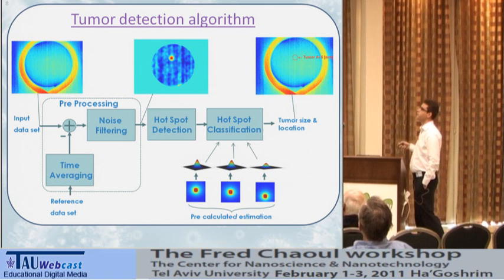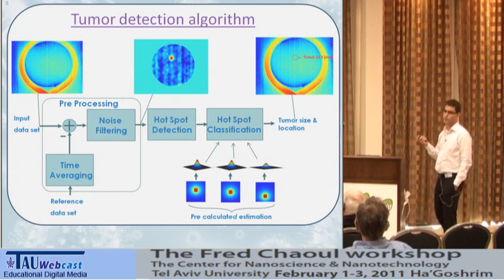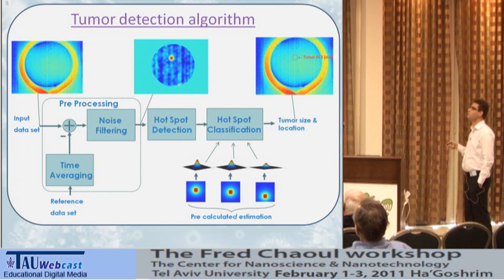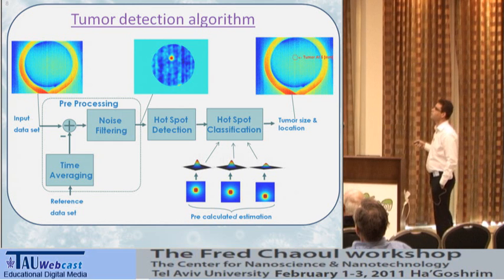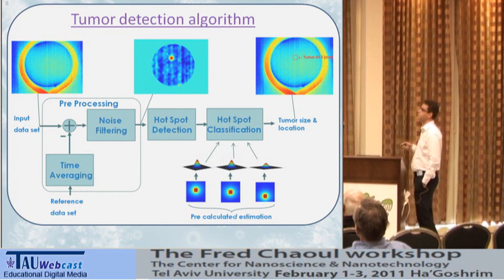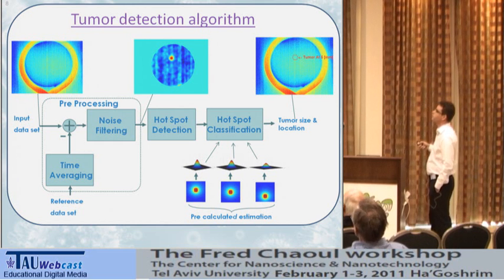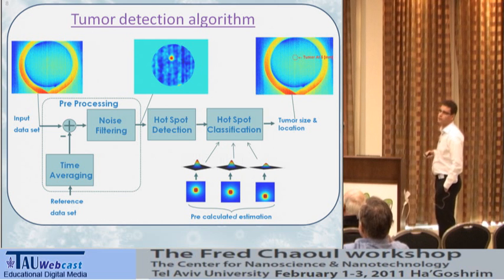So we took this picture, we subtracted the reference picture from it. We took only the region of interest. And when you look only at the region of interest, we also did some special filtering. And then you can see the hotspot very nicely.